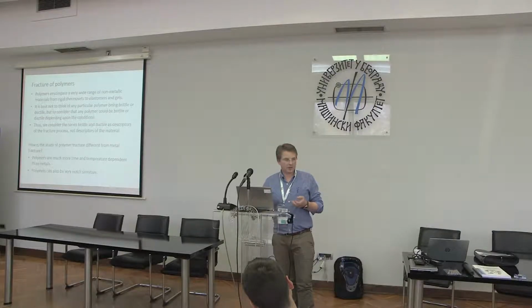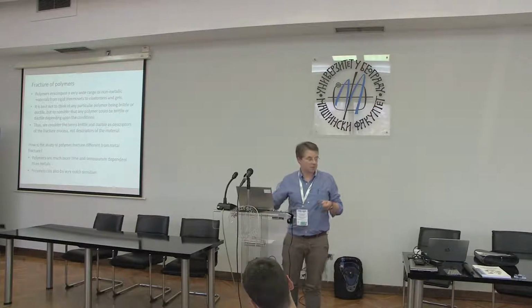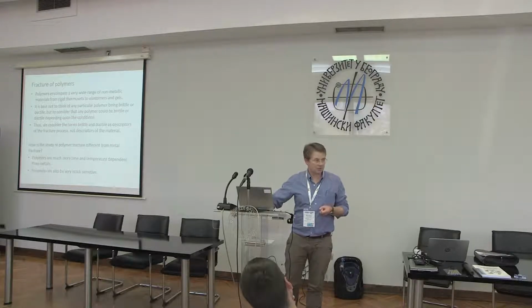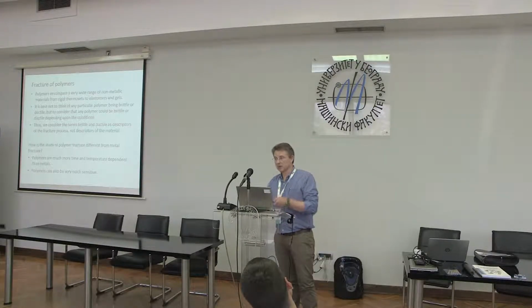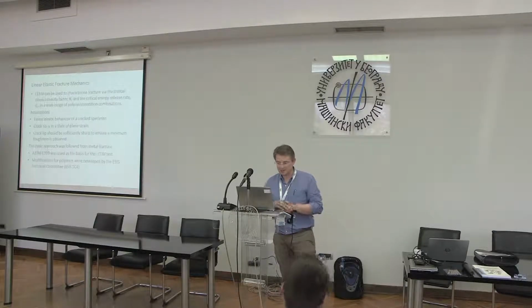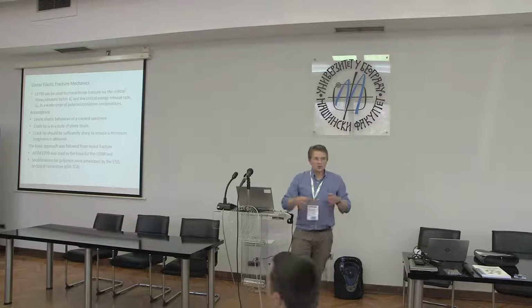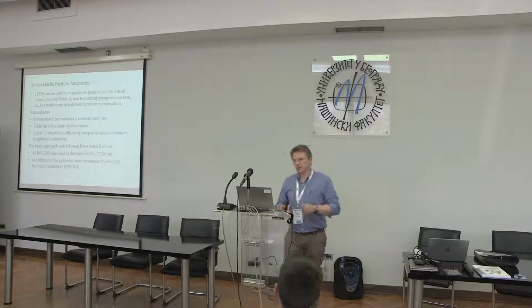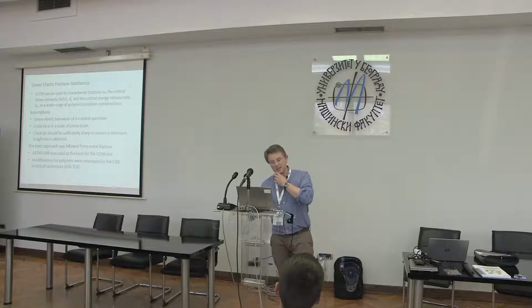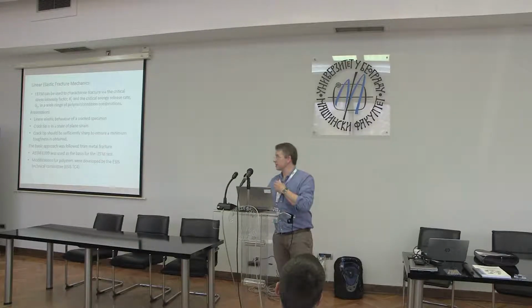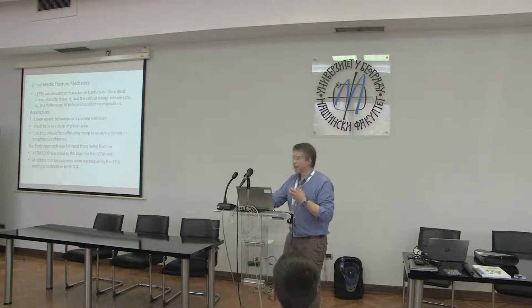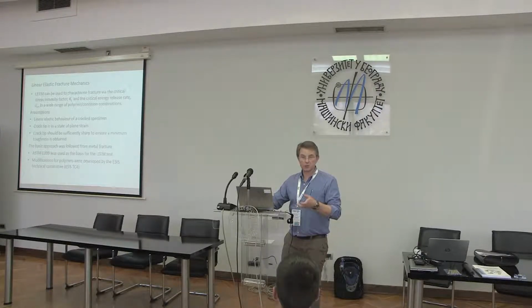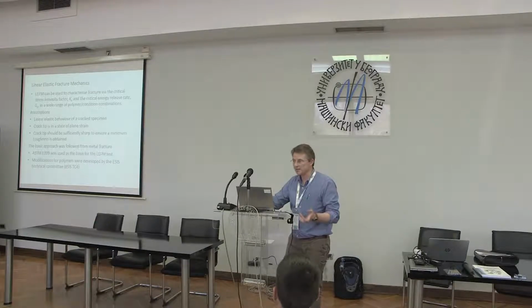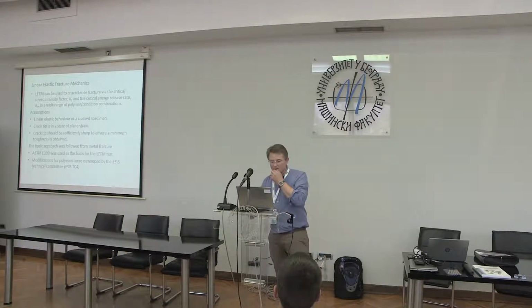So we have to worry intensely about the situation of the initial notch. This has a big implication on the results that we always obtain from these standard methods. So just thinking about going down that left-hand column of my diagram, we're looking at linear elastic fracture mechanics here, where we're using LEFM to characterize fracture either via the K parameter or the G parameter. So stress intensity factor or energy release rate.